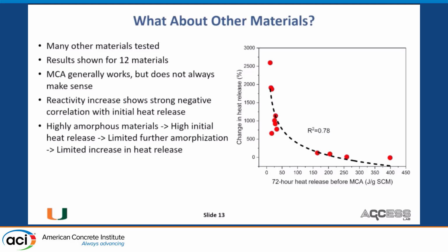So generally speaking, this works fantastically for filler materials, for materials which have very, very low values of reactivity. But going forward, it's not useful to do this. I would not do this, especially because it's a pretty energy intensive technique, for a fly ash, for example. So that's the explanation that I just gave, that the highly amorphous materials have already high initial heat release. There's limited further amorphization, so limited increase in heat release.